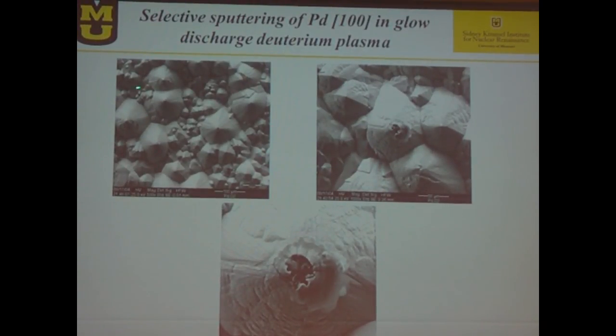And actually, all those pyramids are recrystallization of the palladium after being liquefied and evaporated due to the bombardment of ions. And here you can see the scale. So it's quite big chunks of palladium and a very modified surface, which increases the probability for getting excess heat.